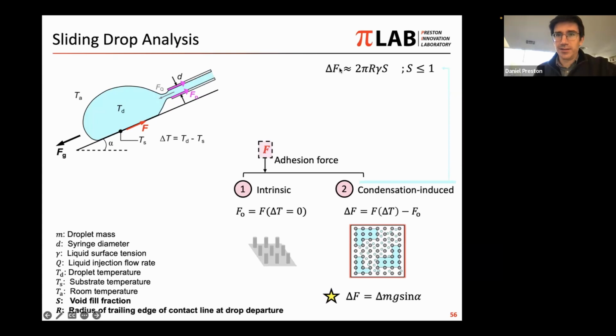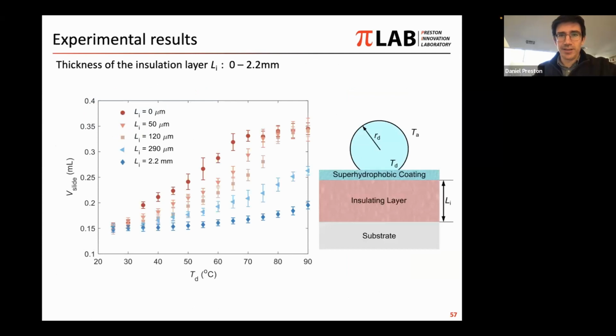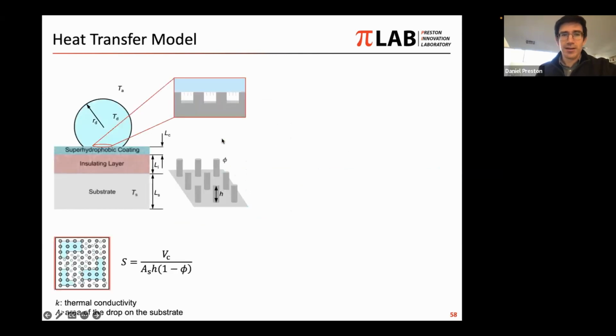So certainly we can have this delta F if we fill in some fraction of the unit cells such that this S, the fraction that's filled, is less than 1. But we can also imagine filling them all, and this is the maximum adhesion force or the maximum delta F that we can get. And so we should have some plateau with this. And so we can see that that plateau also arises up here in terms of the sliding volume. So we have increase. And not only that, but we've also done this for many different thicknesses of the insulating layer. And we see that as the insulating layer thickness goes down, we have more sliding volume or more adhesion. And so this is due to this evaporation and recondensation mechanism.